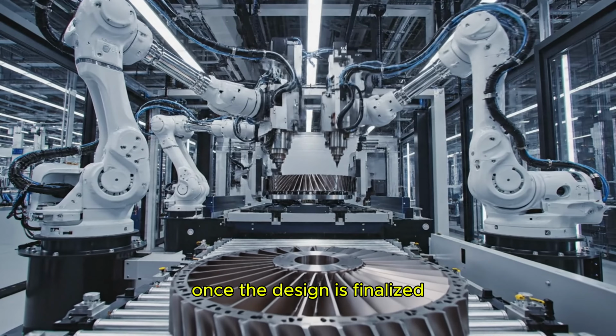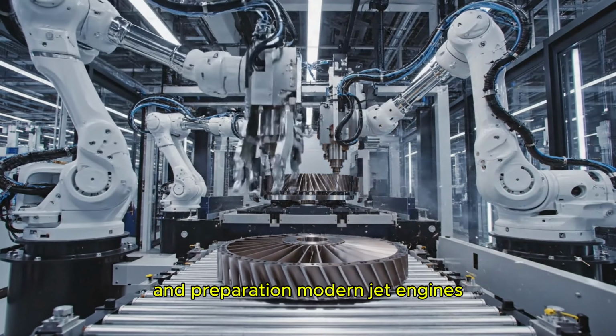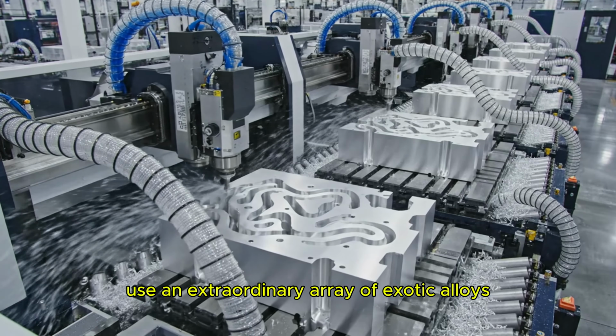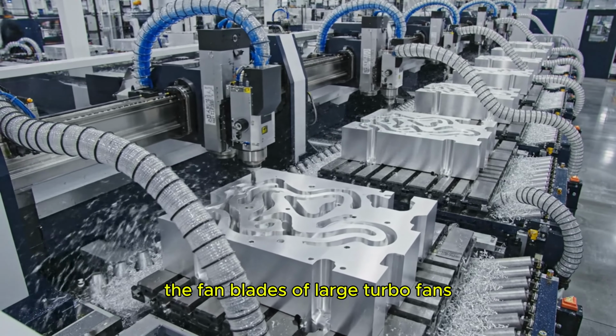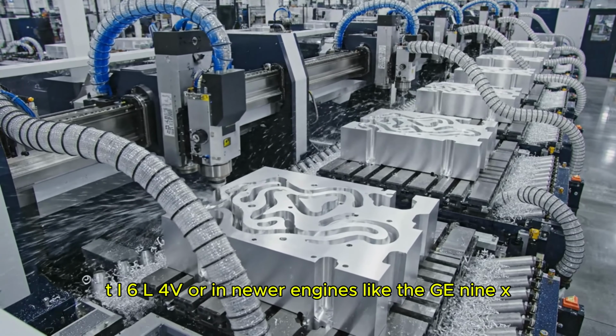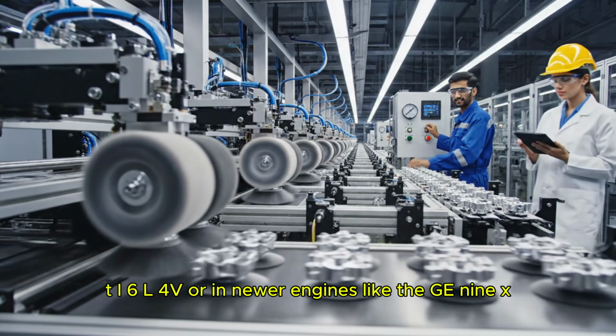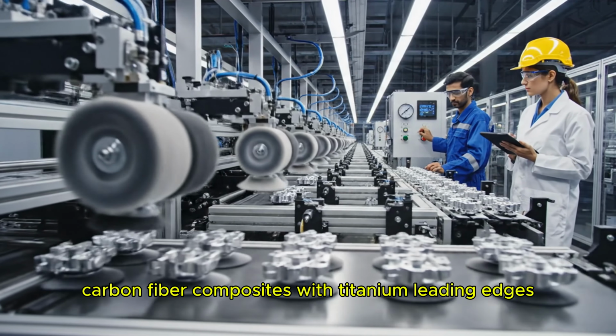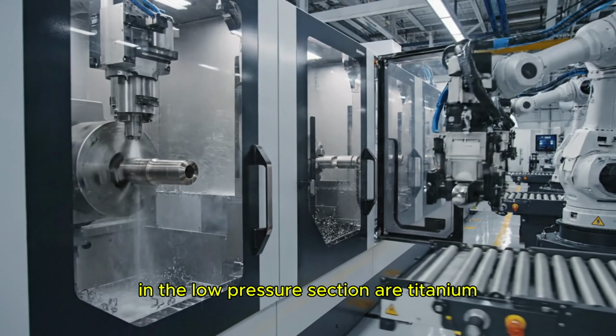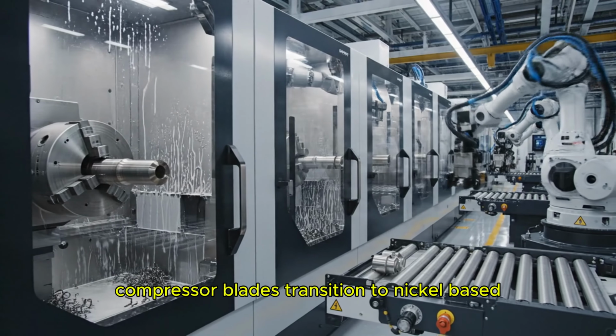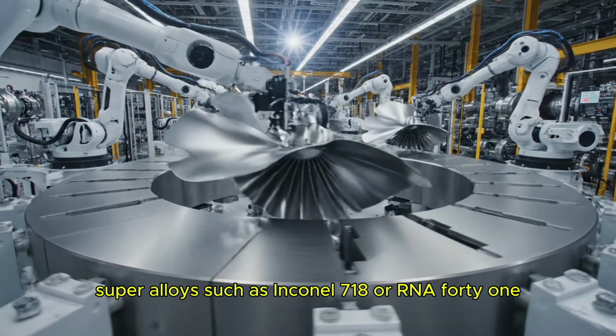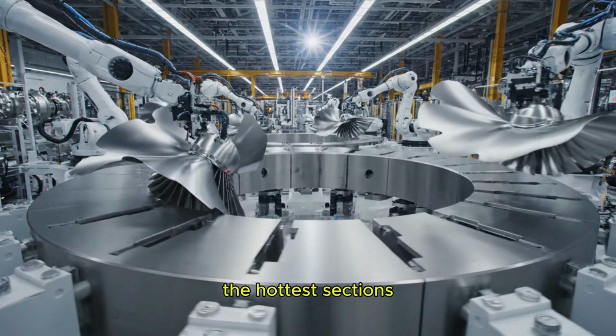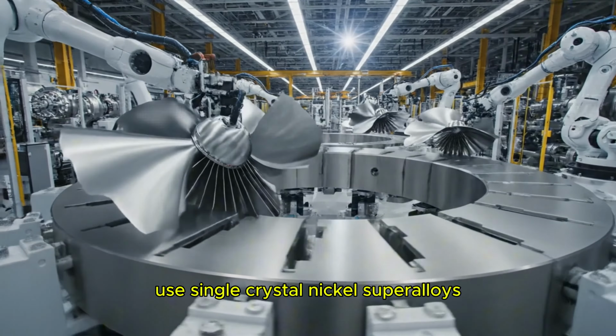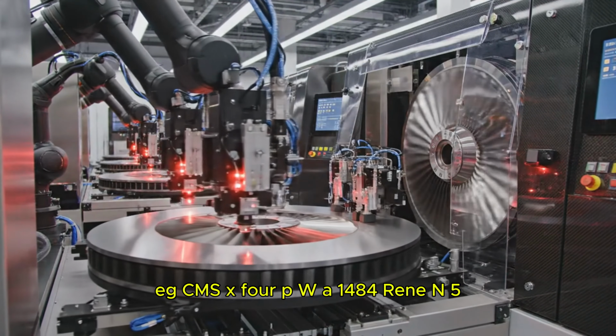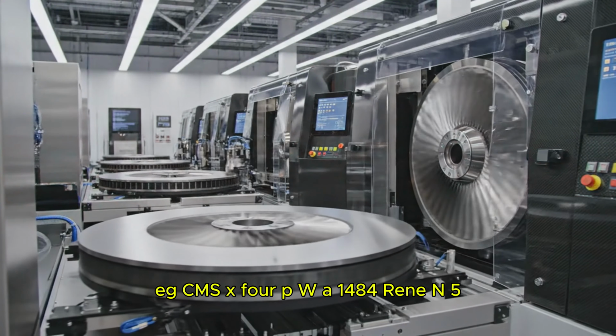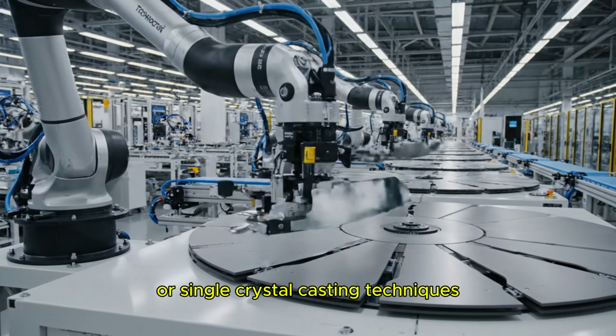Once the design is finalized, the first critical step is material selection and preparation. Modern jet engines use an extraordinary array of exotic alloys and composites. The fan blades of large turbofans are typically made of titanium alloys, Ti6Al4V, or, in newer engines like the GE9X, carbon fiber composites with titanium leading edges. Compressor blades in the low-pressure section are titanium, while high-pressure compressor blades transition to nickel-based superalloys such as Inconel 718 or Waspaloy. The hottest sections, the combustor and high-pressure turbine, use single-crystal nickel superalloys, CMSX-4, PWA 1484, Rene N5, grown using directional solidification or single-crystal casting techniques.